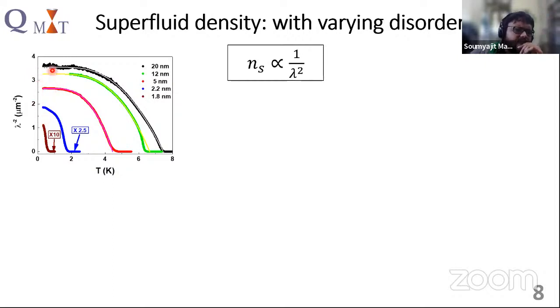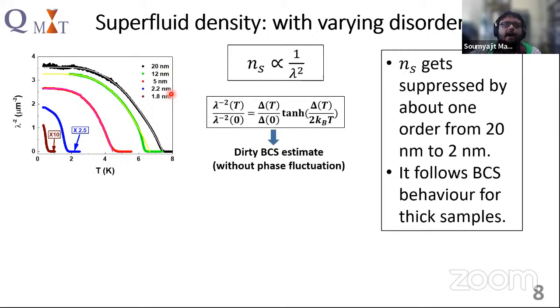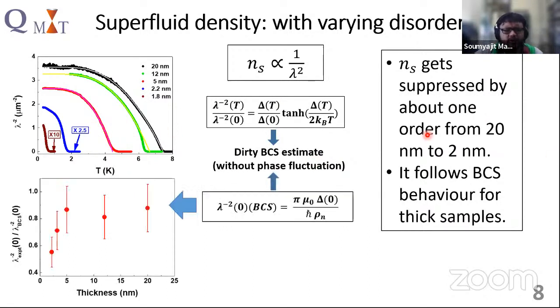So here you can see that the 1 by lambda square falls by around 1 order if we go from 20 nanometer to 2 nanometer. And also we could fit the curves in the higher and higher thickness, for the 12 nanometer and the 20 nanometer, by the dirty BCS fit by this formula.